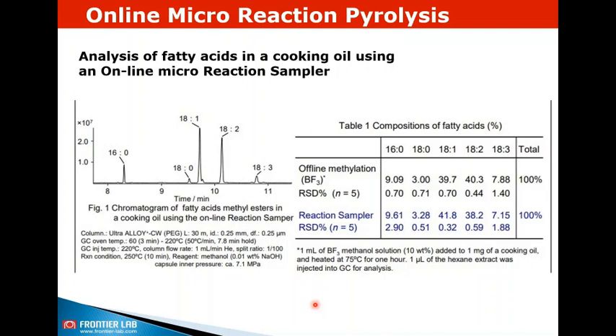So what we have demonstrated here is that if you are using our micro reaction sampler, you don't have to use boron trifluoride. You can just use methanolic sodium hydroxide to do this methylation, and you can get very good profiling that has very good reproducibility and is in good agreement with the standard method of offline methylation with boron trifluoride. As I said, people do not prefer to use boron trifluoride because of its toxicity, and when they see this is an alternate method that can give you the same or better results with better reproducibility, this is the best thing they want to have in their laboratory.